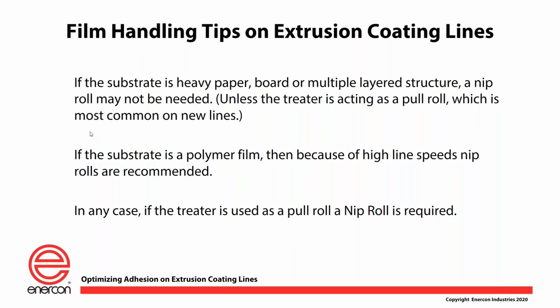If the substrate is a film and the speeds are high and you have very thin gauge film, then typically a nip roll is recommended. And people will ask me, well, what speed is that, Tom? How fast do you have to go before you start thinking about it? Well, in my experience, I started looking seriously at incorporating nip roll designs in our treaters when you start getting in that 700 foot per minute or higher.